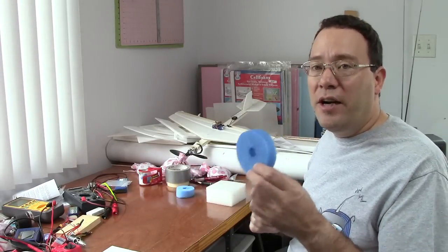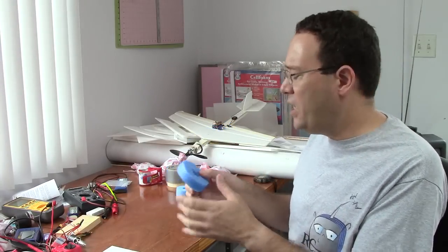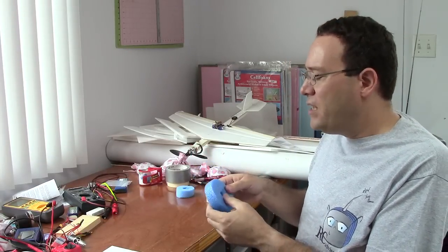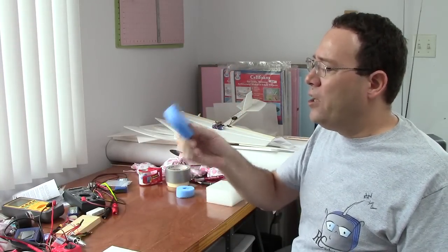Now pure EPP has an advantage over every other foam that at least I'm aware of which is it's got really good heat resistance. Normally we don't care but some of these foams start to lose some of their strength when it gets really hot. EPP is rated up to 212 degrees Fahrenheit which is 100 degrees Celsius.